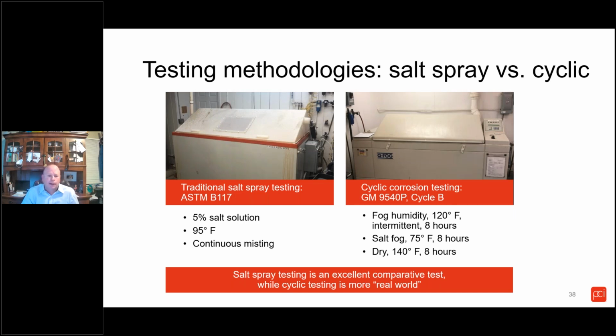The other type of testing we're seeing more and more of is cyclic testing. Traditional salt spray testing is a 5% salt solution at 95 degrees Fahrenheit, a continuous mist, except for the hour or so when the lab tech is checking or adding parts. It's a continuous process.